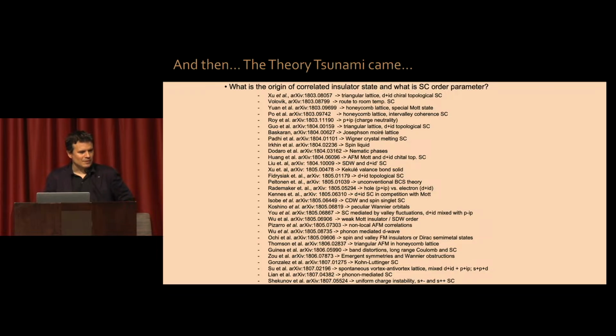I always joke with people that in the field of single particle physics, like, when you do vanilla graphene, just one layer, the angle of disagreement between the theories is about 20 degrees, more or less. They have some differences, but they mostly agree. In this field of many particle physics, interacting physics, the angle of disagreement is 360 degrees. In fact, it's 4 pi, it's in all directions. So theories do not agree at all with each other. There are many fights. Which assumption did you take? Which approximation did you make? I don't agree with you. For me, sociologically, it has been very interesting to experience this.